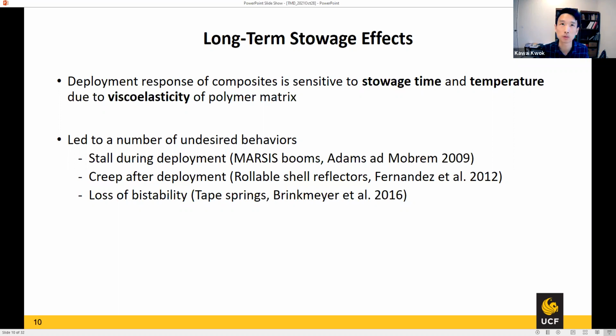So I worked on this, starting from the last year of my PhD, and it's still a relevant problem today. If you roll up or fold composite structures and keep them in a deformed shape for too long, because of the viscoelasticity of the polymer matrix, the deployment becomes a lot more difficult to handle, and there are some unexpected behaviors. Some of them are not very desired. Sometimes the deployment actually gets stalled in the middle, so you don't have a full deployment, while we expected it to come back completely for just an elastic tape spring.